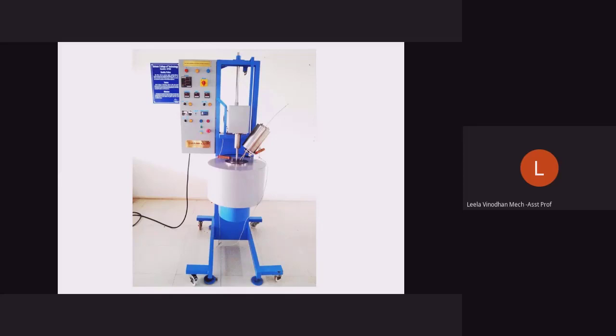After that, you can add the reinforcement, whatever reinforcement you want to add. Then stir it for quite a bit of time. It actually varies, depending on the reinforcement. It varies with respect to the stirring. You will choose a particular RPM, and then we allow the stirrer to stir the aluminum material and the reinforcement material.